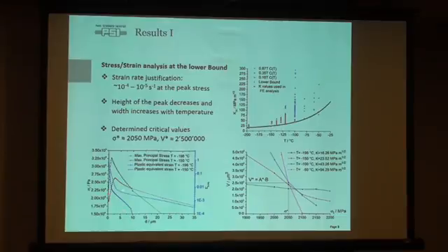If we have a look again once more at the stress ahead of the crack tip, it seems that the stress, at the lowest temperature we investigated, has to act at least over a width of one prior austenite grain size.